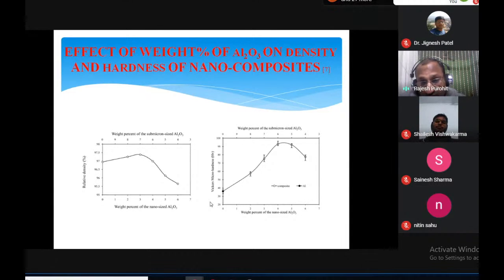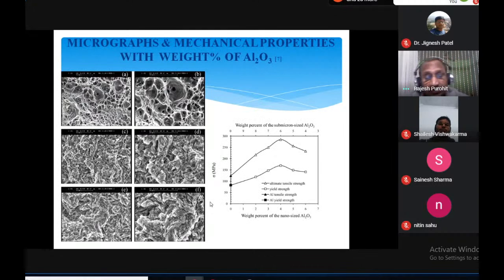The other graph is showing Vickers microhardness values. Here also we get the highest value at about 4.5, and after that it decreases. So everywhere, properties first increase and then decrease, because at higher weight percent segregation takes place, particles do not mix, and bundles of particles form, which reduce the properties. These are micrographs showing the mechanical properties with weight percent of aluminum oxide. Some show dimples and some show porosity, and the right graph shows the strength with variation of the weight percent of nano aluminum oxide. The bottom curve shows the yield strength, and the upper curve shows the ultimate tensile strength.